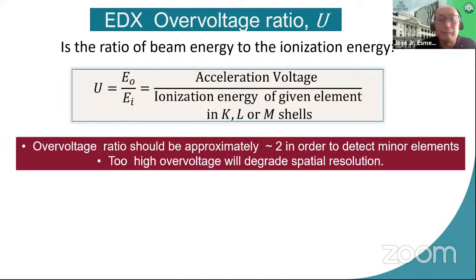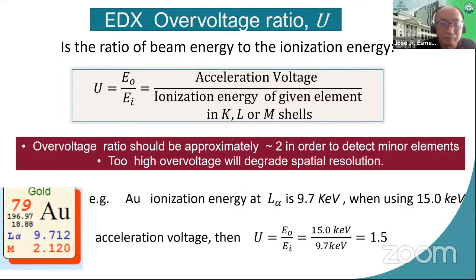EDX needs what you call overvoltage. Overvoltage is the ratio of beam energy to ionization energy. That means you need to use a higher acceleration voltage in order to identify more elements. In practice, the ratio should be 2 in order to detect minor elements. A higher overvoltage, I mean 3 or 4, will degrade the spatial resolution. Just an example, if in the table we have gold, ionization energy is 9.7 kilovolts. If I use 15 kilovolts acceleration voltage, that's enough, a ratio of about 1.5. If I want to get more details, I use 20 kV to approach 2.